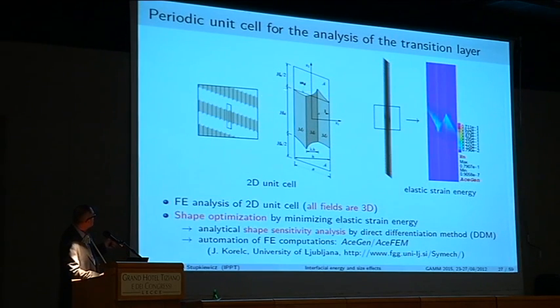So if one chooses in a clever way the unit cell, one can formulate a two-dimensional problem, actually, although all fields are 3D. So we will see in-plane displacements, but there are also out-of-plane displacements, because otherwise you cannot model properly these materials. And then we do shape optimization so that the elastic strain energy is minimized.